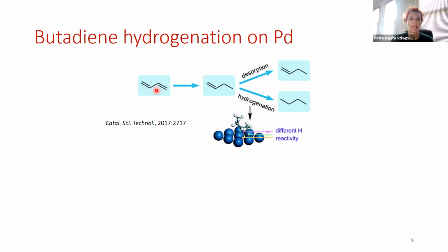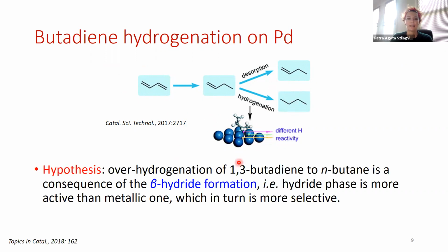And so what we would want is to take the butadiene and only hydrogenate one of these double bonds. But what often occurs is that the palladium catalyst over-hydrogenates the reactant and the undesired butane is formed. And previously, it's been hypothesized that this is a consequence of the beta hydride formation of palladium. So this is the hydride phase, which has not only a high subsurface hydrogen concentration or abundance, but also the ability to replenish the subsurface locations for hydrogen from the bulk. So it was hypothesized that the hydride phase is more active, whereas the metallic one is more selective.